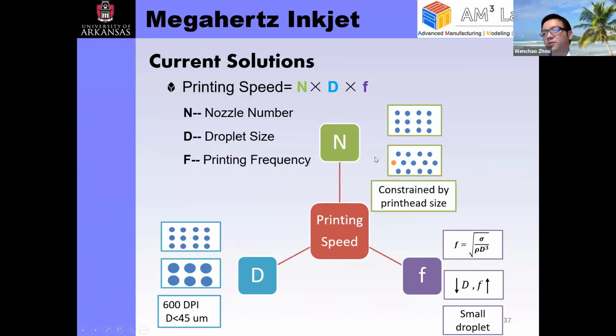As I mentioned, of the three factors, the droplet size and the number of nozzles have been pushed to a very limit. The only way that's been left is the printing frequency. We actually started studying the printing frequency a few years ago, and we revealed that it is fundamentally limited by the surface tension of the fluid, based on the scaling analysis here, where sigma is the surface tension, rho is density, and d is the nozzle size. The thing about surface tension is that you cannot really increase it too much. Other than mercury, water is probably the one that has the highest surface tension you can get.